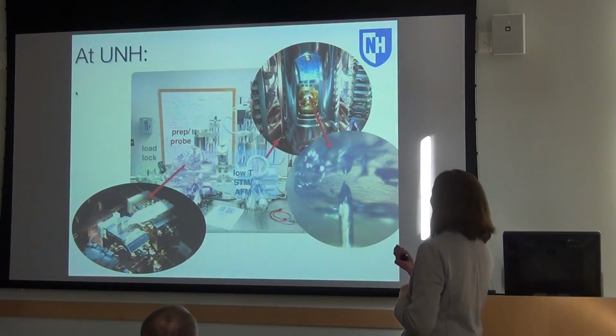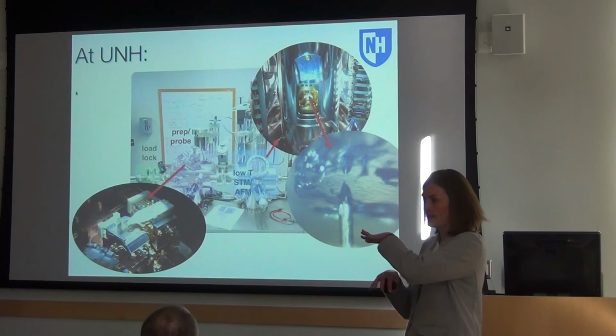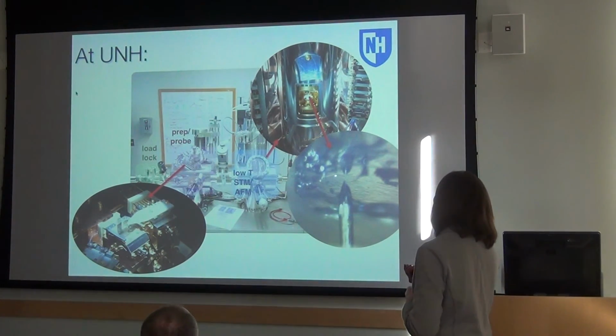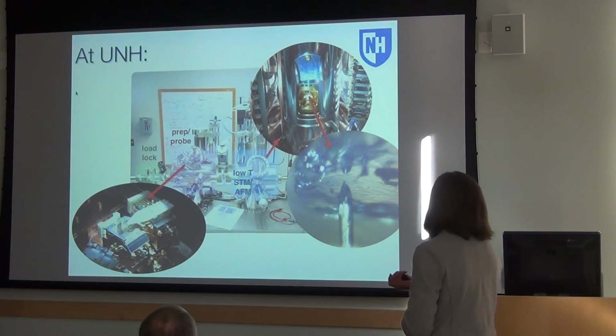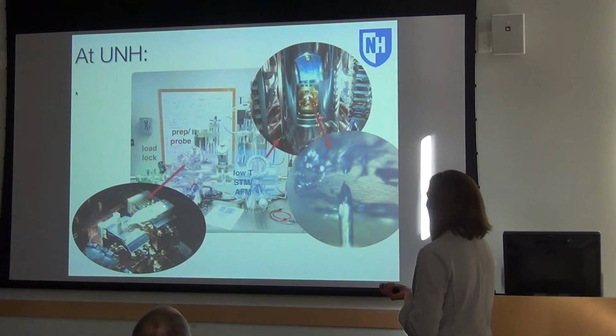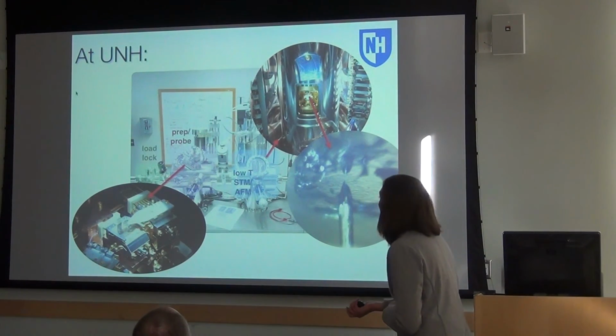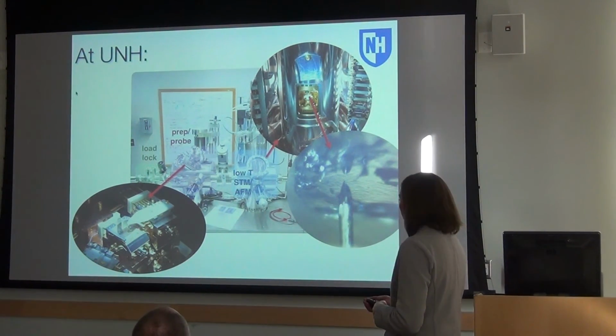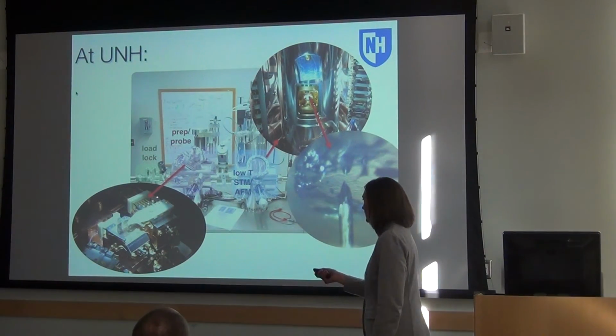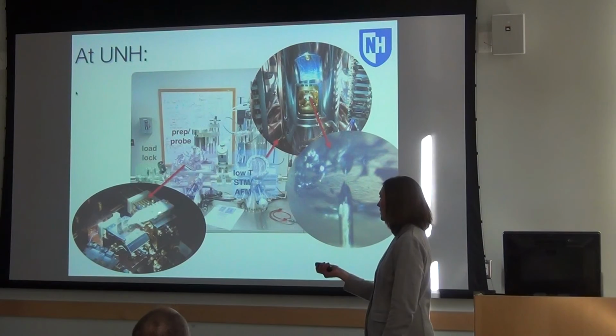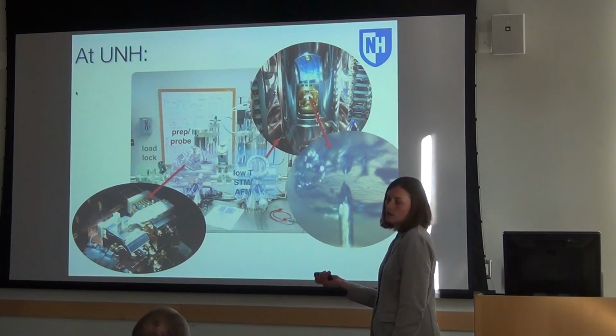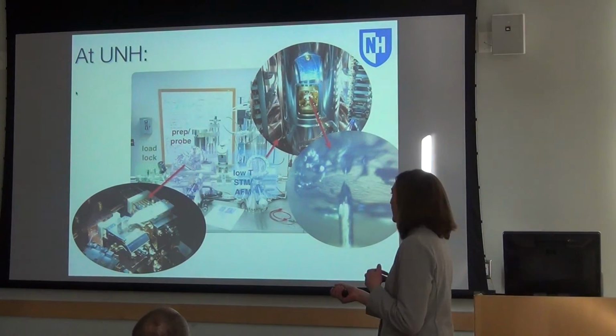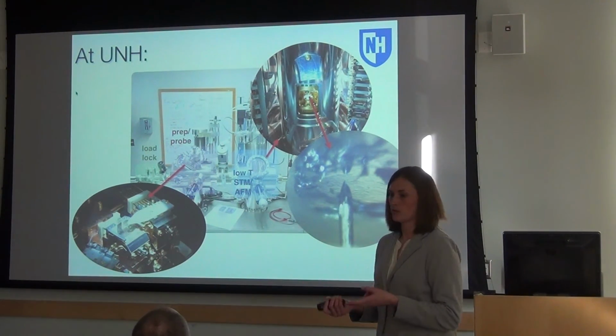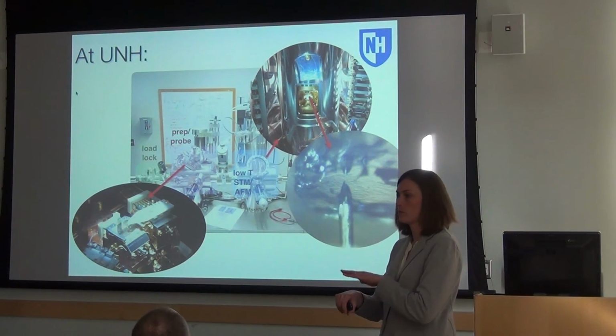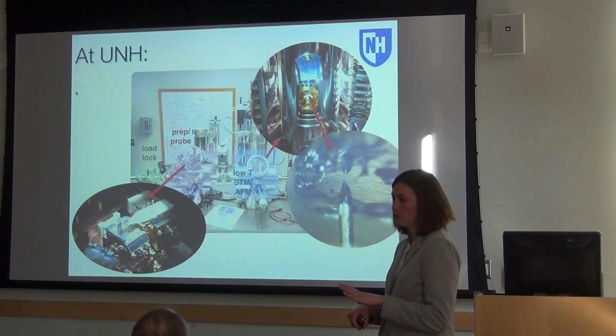So this is the low temperature end, and the tip in this instrument actually points up, and the sample hangs above it. So this is the tip near a graphite sample. And on this side of the chamber, this is the probe station that I was telling you about, and it is still in development. But the idea is that there's this V-shaped plate that we can modify to put different probes on the end. So what we can do initially is just put some wires there to make 4-point contacts, but that's not really the scale we want to be working at.